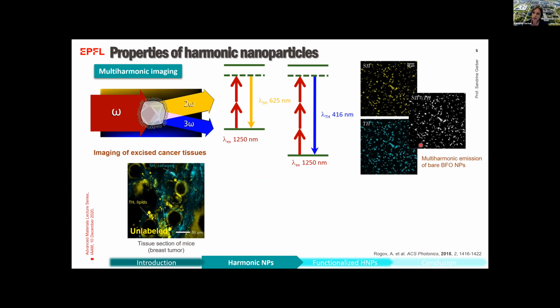So for example, here you have the multi-harmonic emission of bare bismuth-ferrite nanoparticles, where you can see both the second and the third harmonic signal. And here, the image colocalizing these two emissions.